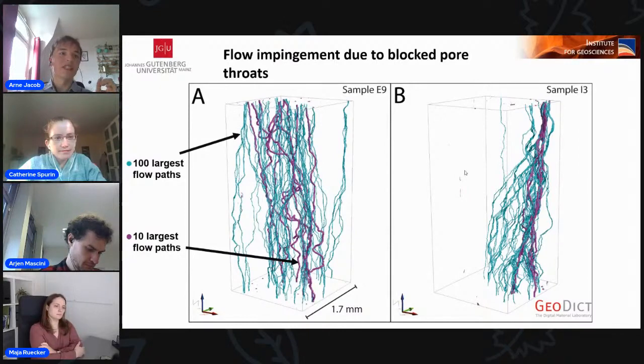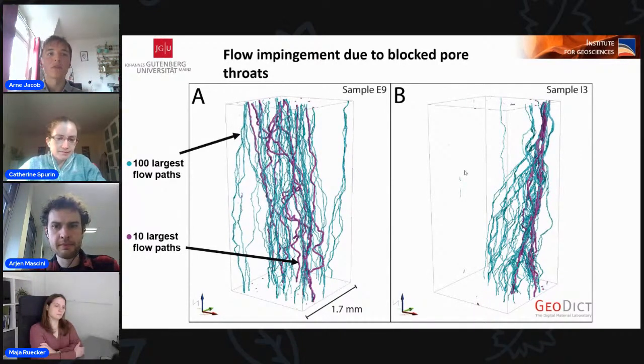You can see on the left-hand side that the structure's largest flow paths are more or less evenly distributed, while on the right side, the flow is controlled by only 3 or 5 pore throats. This occurs when structures are cemented by calcite or other pore cements, or the resolution is just too low to resolve the pore throats. The result would be an inaccurate permeability calculation of that sample. In the most common case, the permeability would be calculated too low. We did not include these samples with a bad flow impingement into our calculations in order to preserve accurate results.